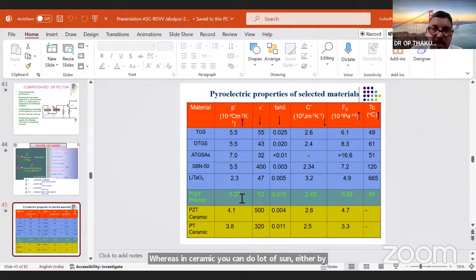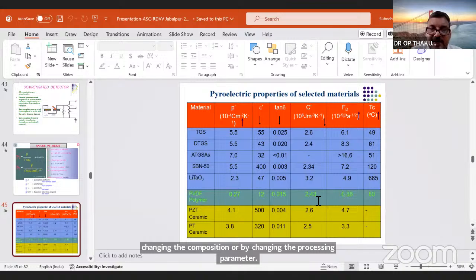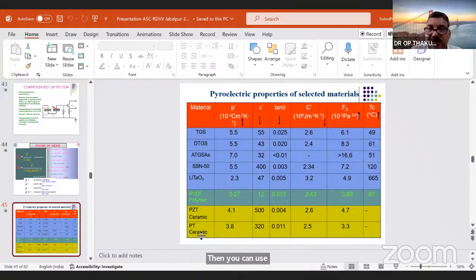Then you can use PVDF polymer for pyroelectric materials, and PZT ceramic and PT ceramics. If you compare the FD, the materials figure of merit, for ceramic it is 4.7, whereas it is larger for the single crystal family. But the flux is very high, so you do not need a very sensitive kind of sensor element, because sometimes even normal performance material will work. It depends upon your application.